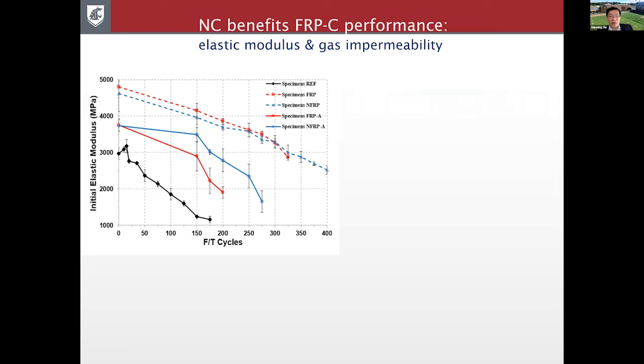Now, the incorporation of nanoclay benefits the performance of this FRP concrete composite. First of all, the elastic modulus on the left, you can see that after the FRP protection, you're seeing some benefits for both the pre-aged group, which is the solid line, and the new concrete group, which is the dashed line.